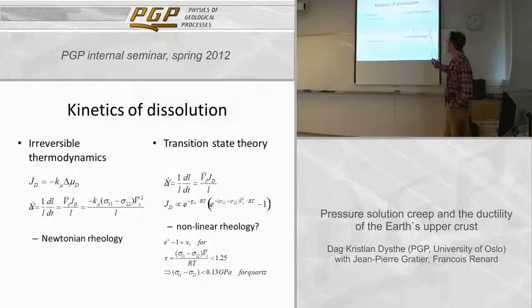Now, when is this? When can we linearize? Well, if we just look at these numbers, it means that for quartz, for example, for stress differences of the order of 0.1 gigapascal, the linear form will be within a factor of 2.